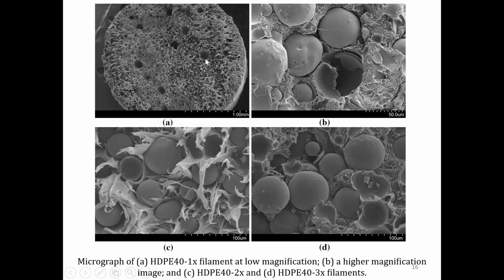Mention what the void volume percentage is, and equally mention that such voids will reduce the weight still further than infusing hollow microballoons. So if hollow microballoons can reduce the weight by, let us say, 25%, these void pockets will reduce it further to 26 or 27%, which is not possible by infusing the hollow microballoons. And this is how we give justification in all our papers whenever we use non-vented type extruders.